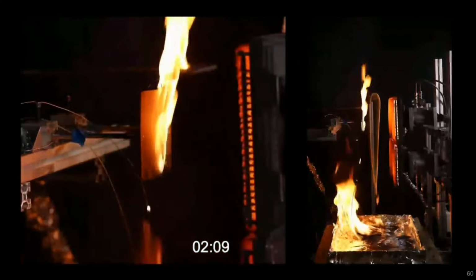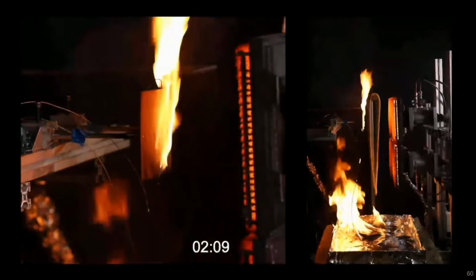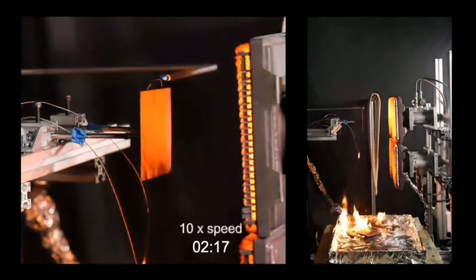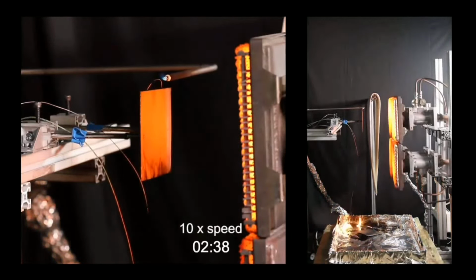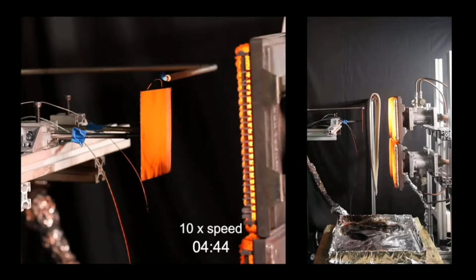At 2 minutes and 9 seconds, dripping ceases, and flaming on the specimen then also ceases shortly thereafter. Between 2 minutes and 9 seconds and 4 minutes and 48 seconds, you'll see I'm running at 10 times speed now. The length of the flames from the polyethylene, which is still burning in the debris tray, gradually decreases until extinction occurs. The experiment is then terminated.